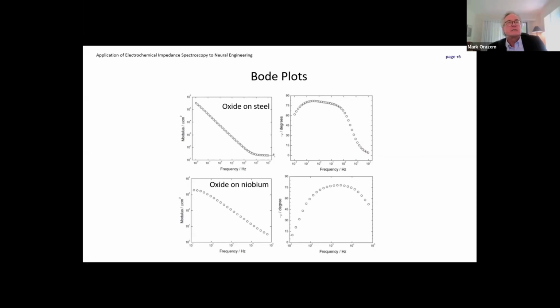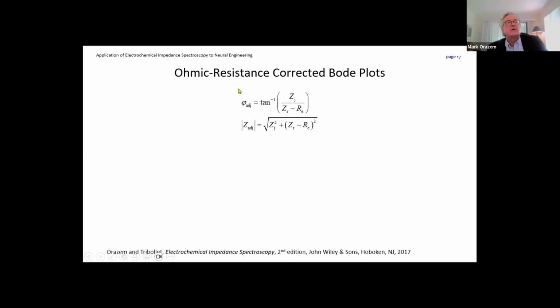The ohmic resistance is a resistor, basically, so that means that the current and potential are in phase, and the phase angle would be zero. And for the oxide on niobium, even though we didn't go to such a high frequency, we can see that we're trying to tend toward zero at high frequency. So our solution to that is to use ohmic resistance corrected Bode plots.